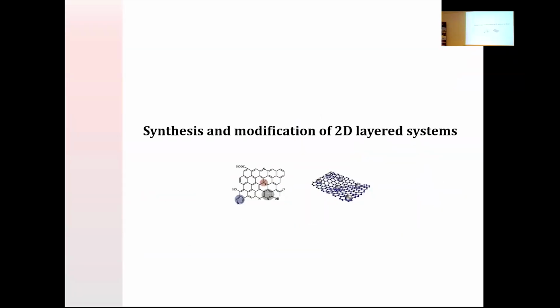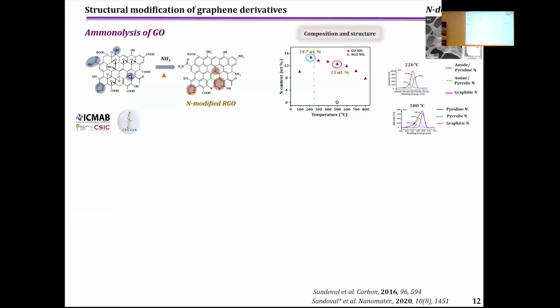Okay, so then I will show some approaches which we are developing in order to improve the properties of two-dimensional layer systems. The first one consists of the doping of graphene using the ammonolysis technique. In this case, we introduce nitrogen, taking advantage of the presence of oxygen groups in graphene oxide. This graphene oxide has been prepared by the Hummers method. Then we use pure ammonia gas. And using this technique, we were able to obtain materials with very high nitrogen content.